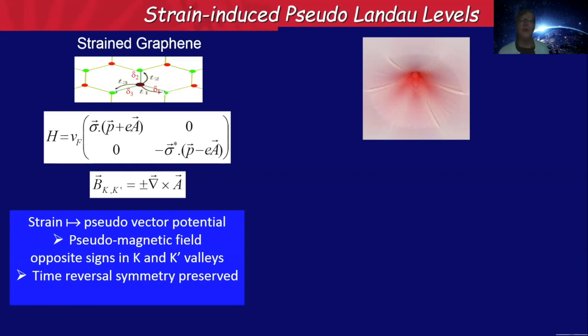So, one way of doing that is to use strain. So here, for example, I have a blister, let's say in graphene, where I'm pushing up, where I'm creating strain, and as a result, the graphene lattice becomes distorted. The hoppings between nearest neighbors, which were previously identical, have now changed. And as a result, the effect of that is to introduce a vector potential, which looks very much like the vector potential that gives rise to a magnetic field.